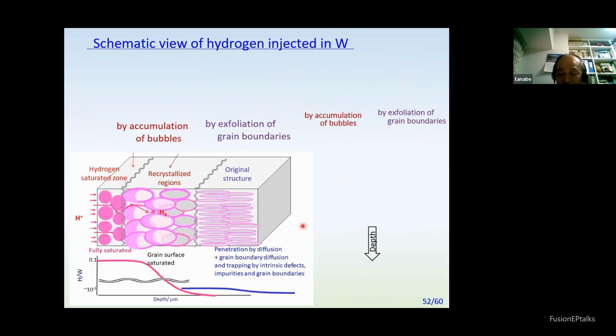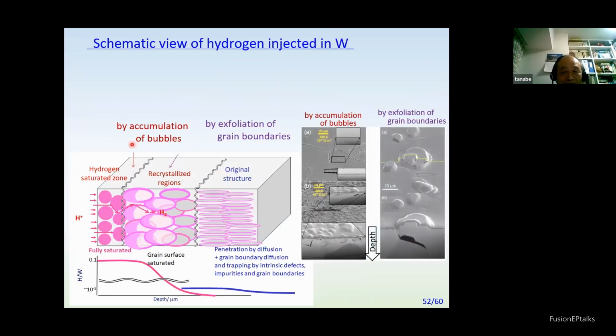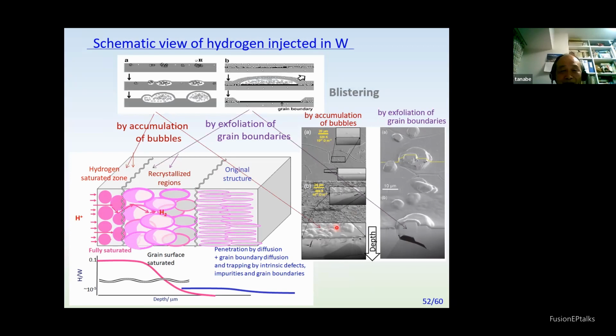How is this possible? In the case of tungsten, hydrogen goes in, making bubbles. Also, high power load changes the structure of the tungsten, causing grain growth. Hydrogen accumulates there and can destroy the grain boundaries, forming smaller bubbles that accumulate near the surface. This change in grain boundaries causes large exfoliation of grain boundaries, but this is quite consistent with the hydrogen profiles and appearance of the surfaces.